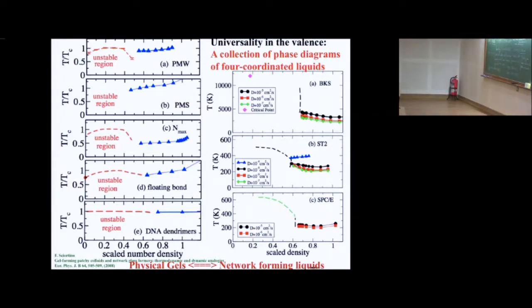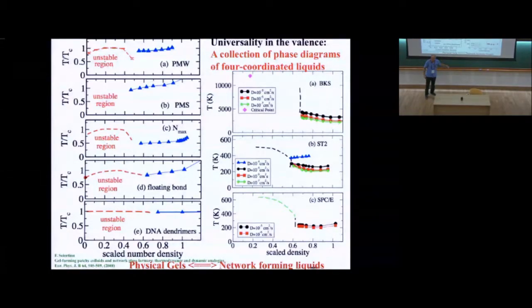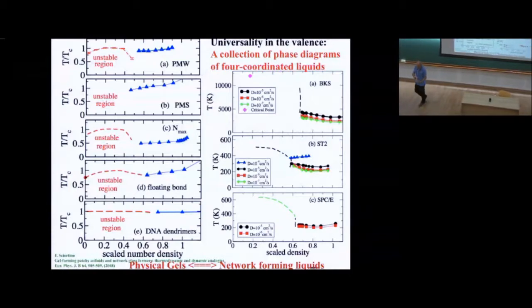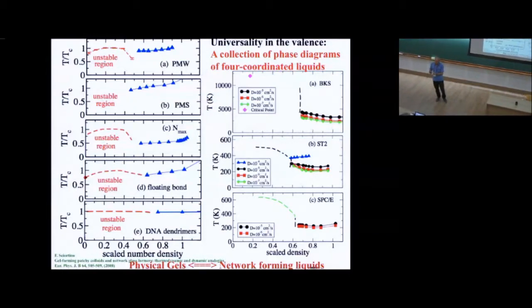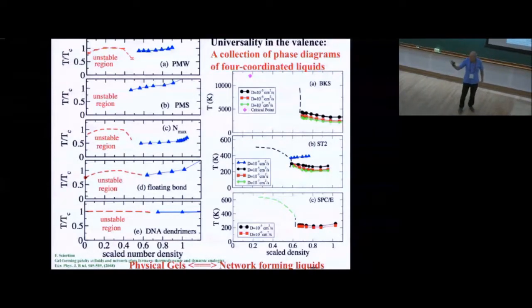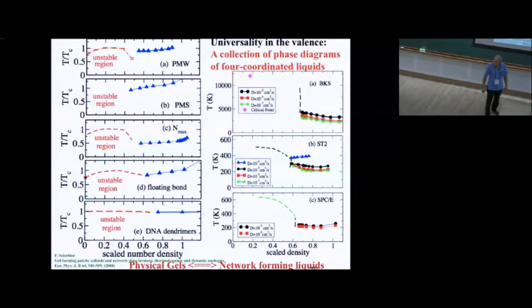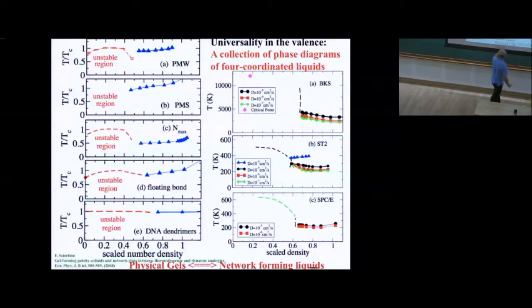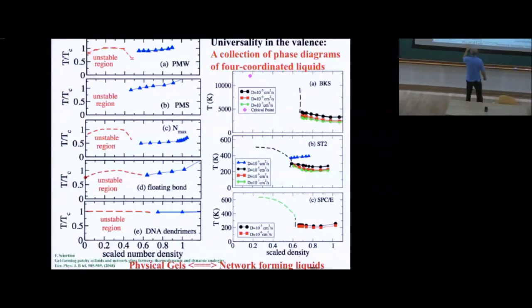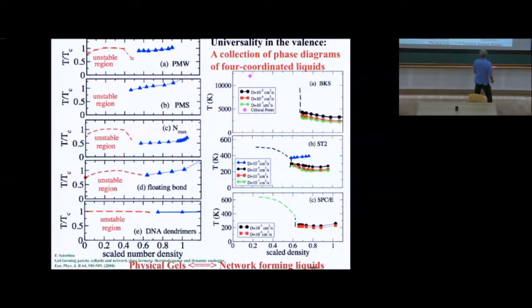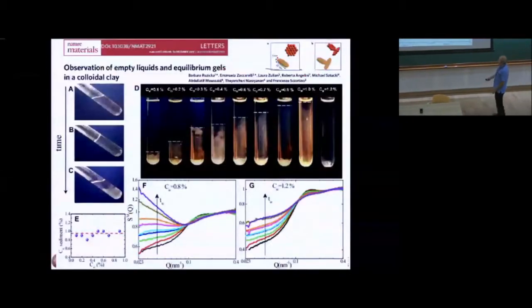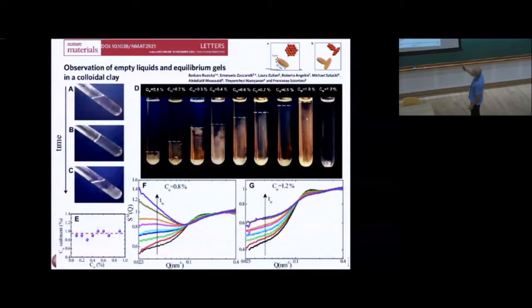No, a physical gel of this type, equilibrium gels. This type of gel you can create in equilibrium because you've moved the phase separation out. And you have moved the phase separation out because the valence is small. So, for example, colloidal gels don't qualify. These depletion gels don't qualify. So physical gel is not the right word. I should say equilibrium gels. Sorry, it's a slip.